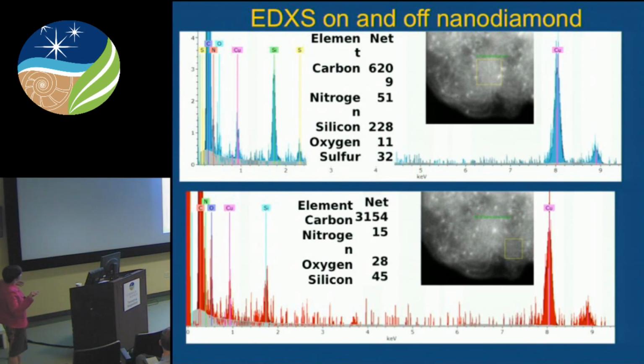But we do think some of these species could be attached at least to the surface and possibly, in some cases, implanted into the interior of the nanodiamond. We can go down from that bulk, 9 nanometer by 10 nanometer.